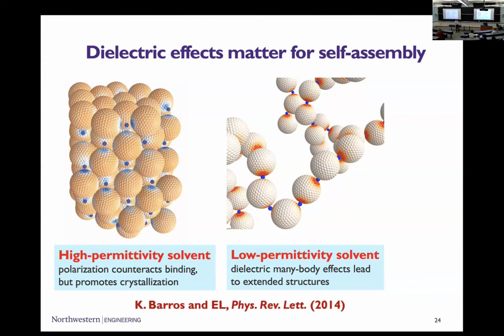And this open structure, of course, nobody predicted that. What I want to note is that the open structure here happens in the case where there is strong binding. The dense structure happens where there is weak binding. Right? That's exactly the opposite. Right? What did I miss? It's a nice reminder of many-body effects, which is, as I said early on, entropy and also many-body effects. That's where human intuition tends to fail.